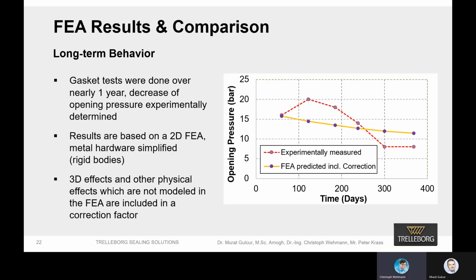Here also we did some tests. So you see, again, it's approximately 1 year test. It's not a linear scale, so that's exactly 365 days, I think. And you see here we have some differences, but in the end, at least we have a rough and I think a good estimation of lifetime. In this case, also we looked at the leakage pressure or opening pressure, which the seal can withstand.